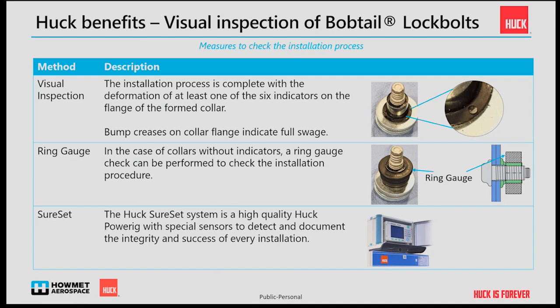We also have some fasteners which do not have swage indicators, but then we offer an alternative solution using a so-called ring gauge. These two methods give you the assurance that the full preload has been applied. When you look at a nut and bolt, you normally can't see if the torque has been applied 10% or 50% or 100%. So that is a very big bonus for using a Lockbolt. So the rework or retightening procedure is completely obsolete. If you need to document the installation procedure, we also offer the so-called SureSet system. This is a device that can monitor and record all the installations, and it can be saved to your quality system.